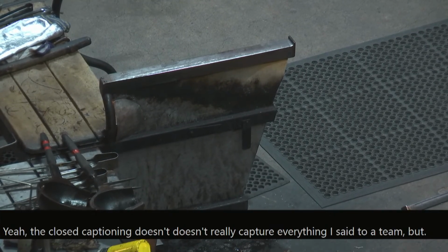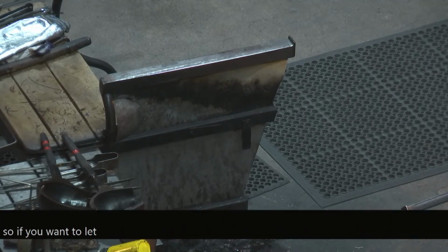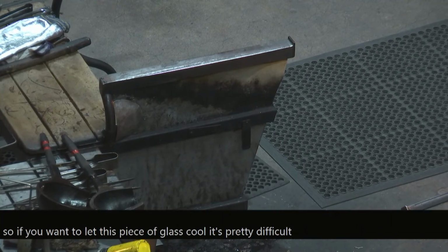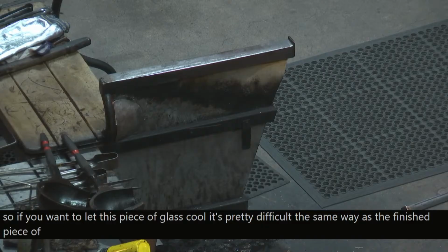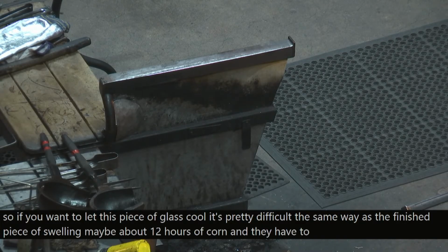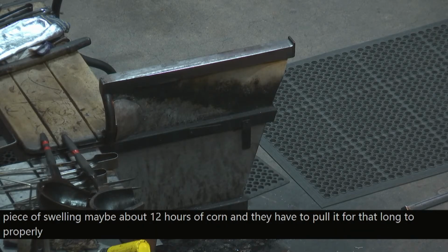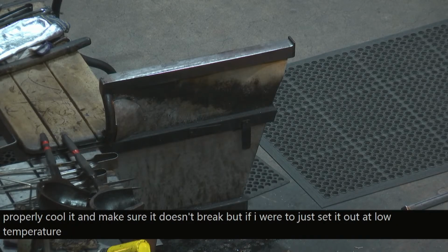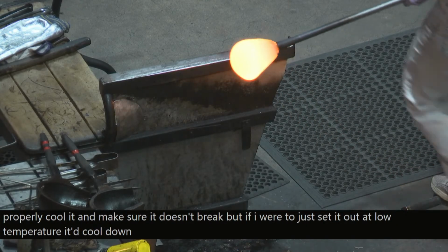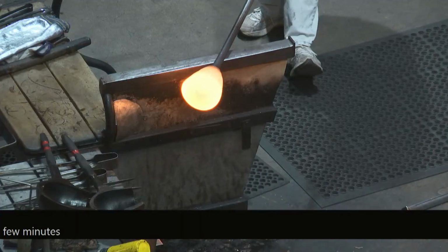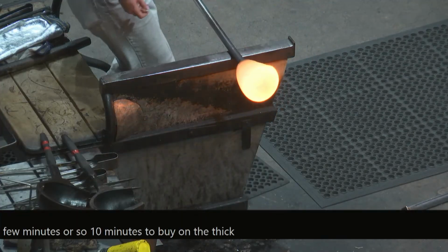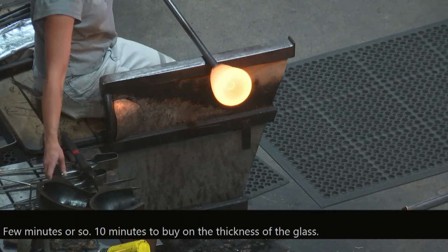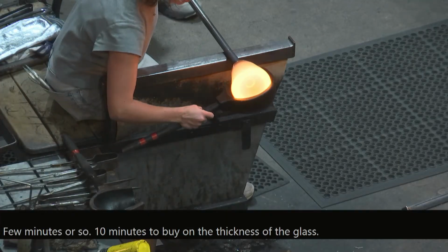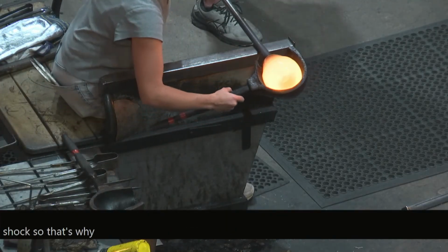So if we were to let this piece of glass cool, it's probably going to cool at the same rate as the finished pieces as well, maybe about 12 hours of cooling. We have to cool it for that long to properly cool it and make sure it doesn't break. But if we were to just set it out at room temperature, it would cool down in a few minutes or so, 10 minutes, depending on the thickness of the glass. But if we do that, then it'll crack from thermal shock. So that's why we cool it very slowly.